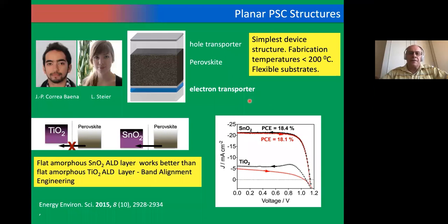Besides compositional engineering at the EPFL, we have also been driving different types of device structures, and this is what we call the planar device. It's the simplest possible device for perovskite. It's basically a negative contact, where we typically use tin oxide as a compact layer. We have then spiro and gold on top, and the perovskite in between. So here we separate the charge in the perovskite layer, and they go then to the selective contacts. This can be made under 200 degrees Celsius, so it opens up for flexible substrates and so on.